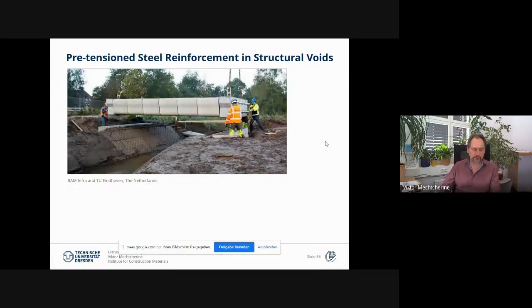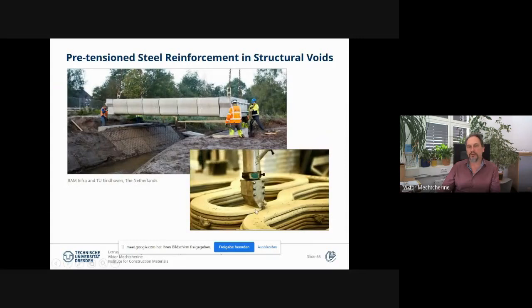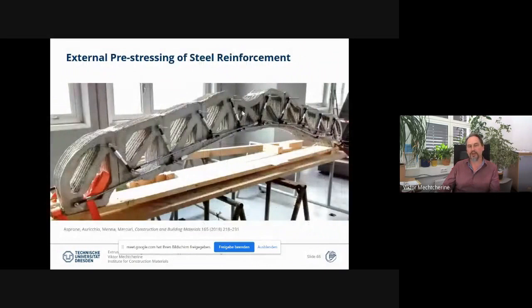Then an example which I showed you already. So you can produce some structural elements with voids, which is often the case for 3D printing with high resolution. And then you have the possibility, of course, to guide the reinforcement through these openings, through these voids, and use it as a common reinforcement or for pre-stressing. External pre-stressing is shown here, again, printed element segments, and then you have here some anchorage, and you connect these elements by external pre-stressing.